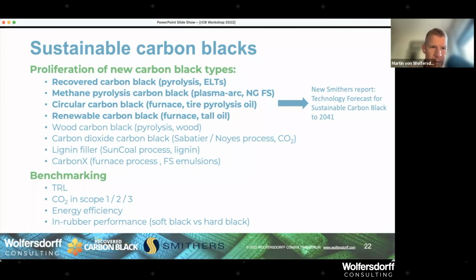in rubber. One little tidbit about the circular carbon black, which is promoted now increasingly by furnace carbon black players, very publicly by Orion Engineered Carbons, and even mentioning recovered carbon black, and even mentioning my specification of RCP1. As good and promising as circular carbon black is, because it is made with tire pyrolysis oil, it is tied to recovered carbon black, and we cannot actually bash or criticize recovered carbon black performance if we want to sell circular carbon black, because for every ton of circular carbon black, there are about 3 to 4 tons of recovered carbon black that have to be sold as well.